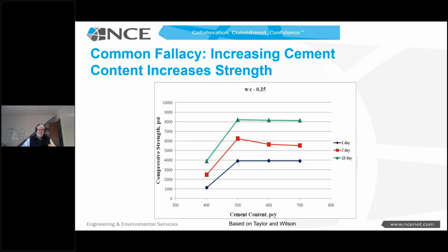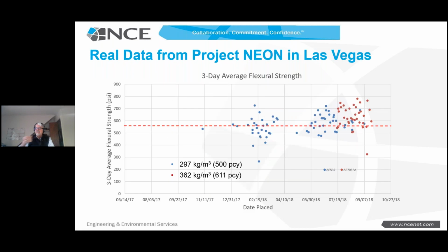I'll put a caveat on that right now: if you need higher strength and you're in an uninsulated type of environment, the additional cement will help your early strength because the extra heat of hydration will speed things up. But there are other ways to address that. This shows work done by Peter Taylor and Wilson at Iowa State University for a given water cement ratio, fairly low at 0.35, with different cementitious contents, and you can see almost no difference in strength at different times once you get past about 500 pounds per cubic yard, once we have enough cementitious material to fill the gaps between the aggregates.